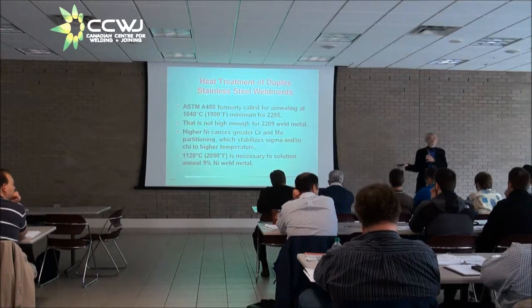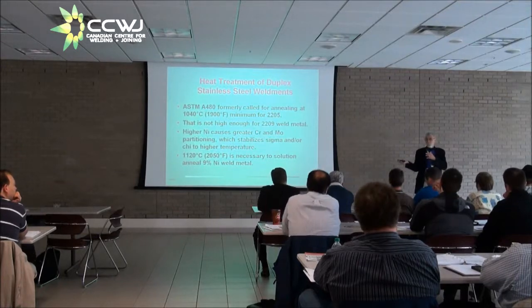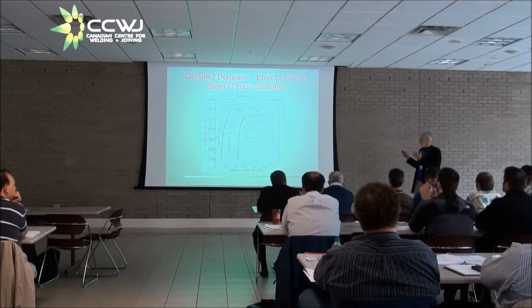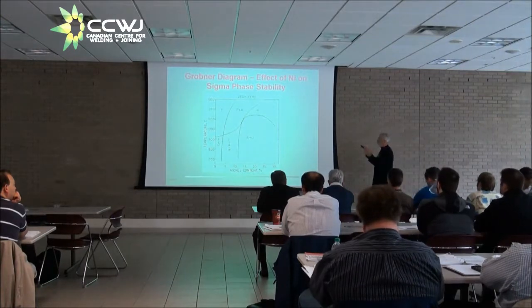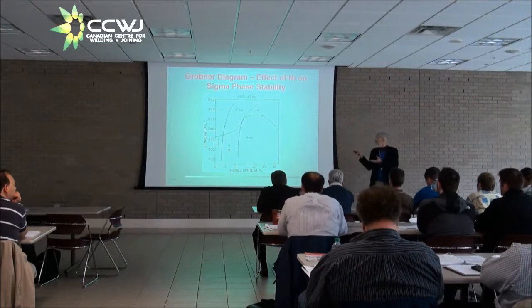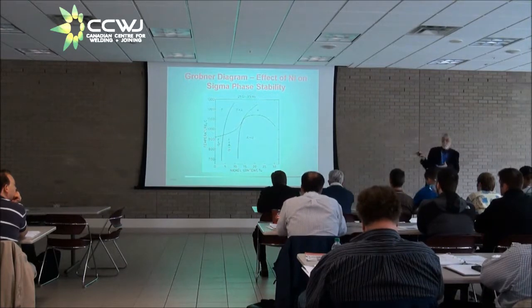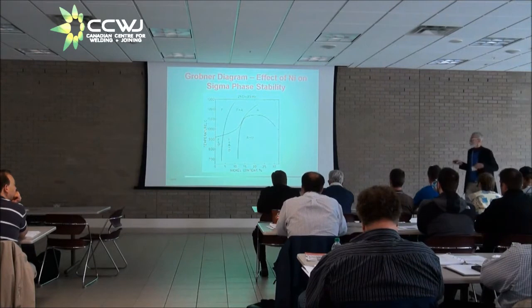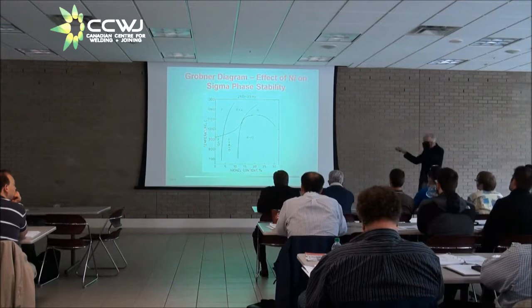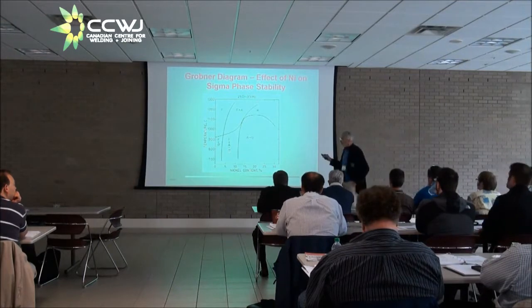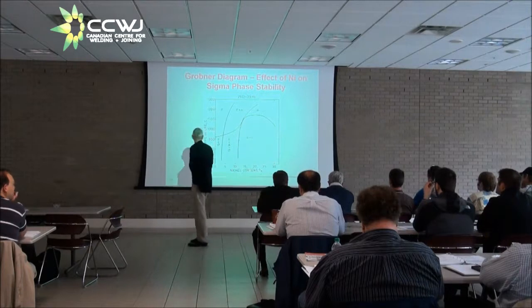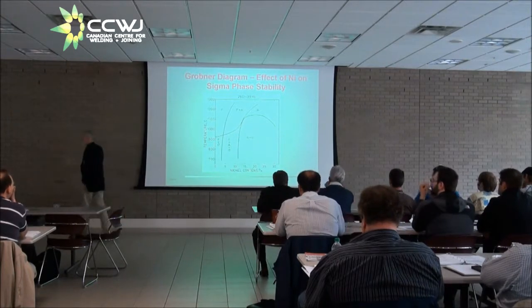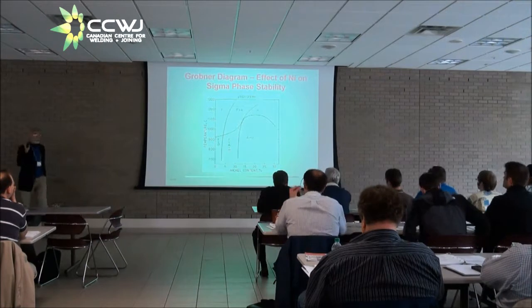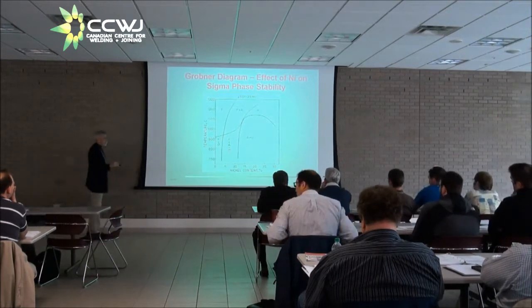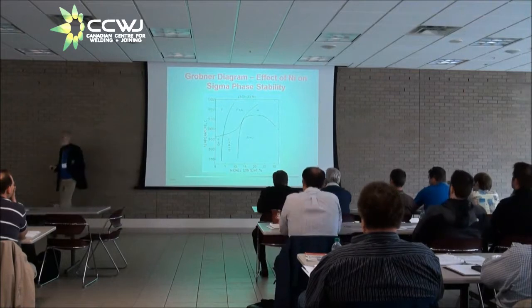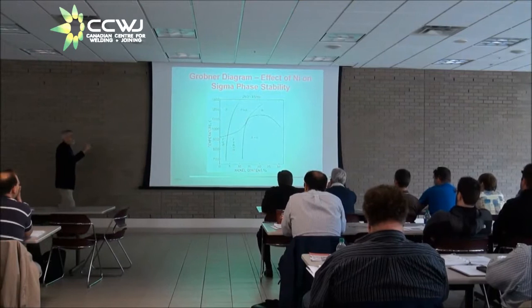Interestingly enough, I gave another paper at the same conference in which I talked about heat treatment of duplex stainless steels. And to begin with, on that paper, I referred back to an old diagram that was developed by a gentleman named Paul Grobner that worked for Climax Molybdenum Company back in the 1970s and 80s. His diagram, which I show here, is looking at the phases that are stable as a function of temperature in a 25% chromium, 3.5% molybdenum alloy with varying amounts of nickel. So what you have on the horizontal axis here is nickel content increasing from 0 to 30%. And all of these alloys contain the same amount of chromium and molybdenum.